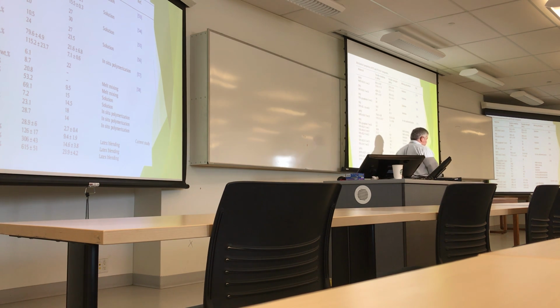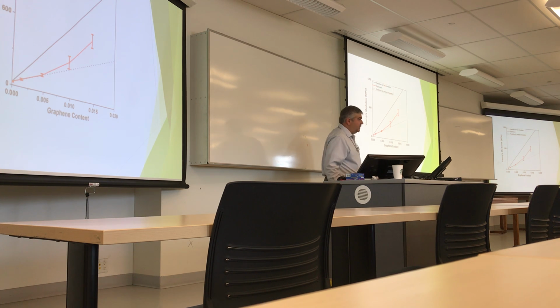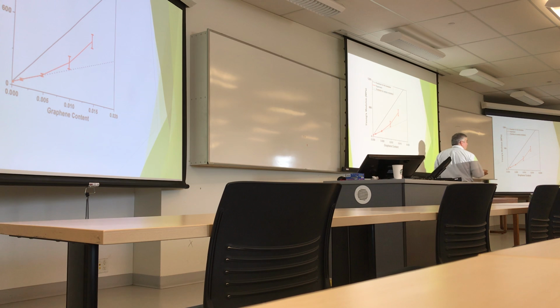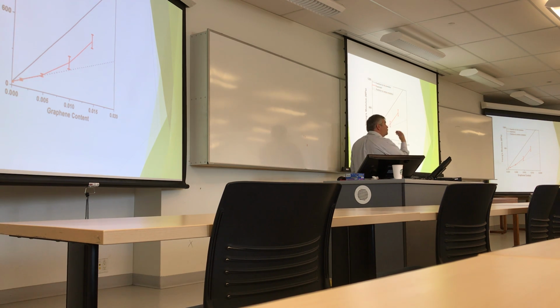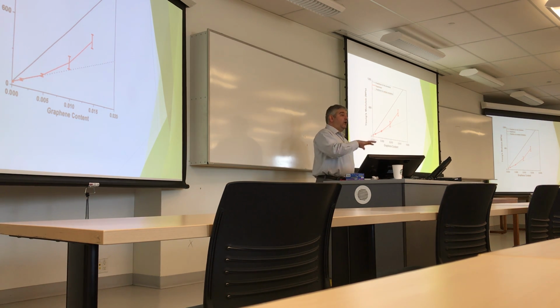And the reason was that, as we found out, and I can show you in the next slide, when we had a high concentration of graphene, the graphene that we were using was quite large. They tended to align themselves, and they kind of created some sort of anisotropy. What you see here is the prediction of the modulus based on Halpin-Tsai, which assumes random distribution of the particles. This is based on the fully oriented, and these are the results that we got. As the graphene content increased, it started leaning towards more orientation. So this was another interesting observation about the graphene. The large particles and higher content made alignment much easier.